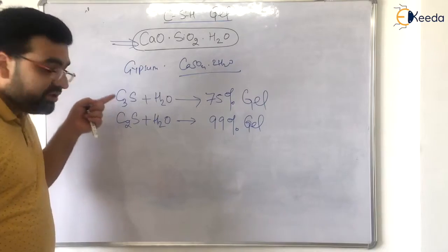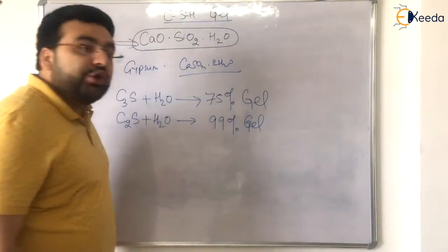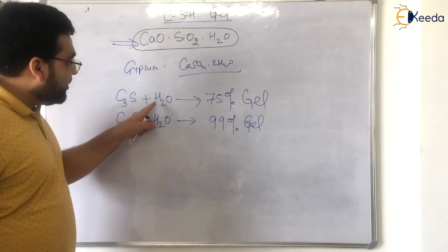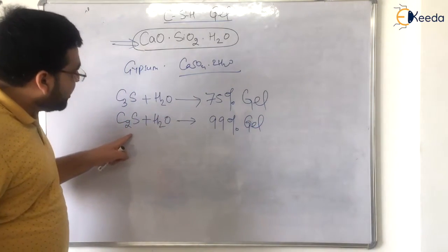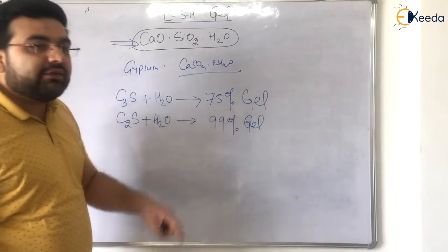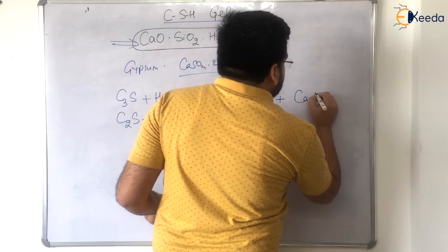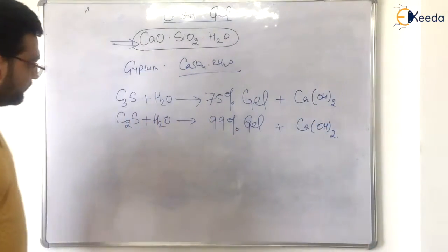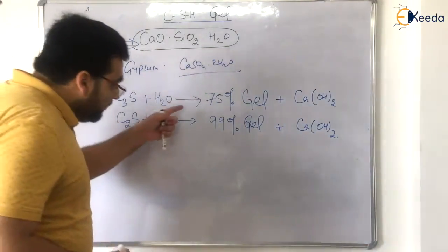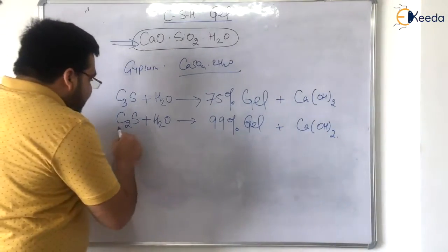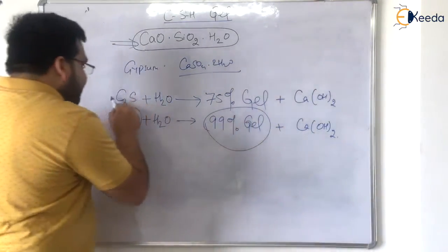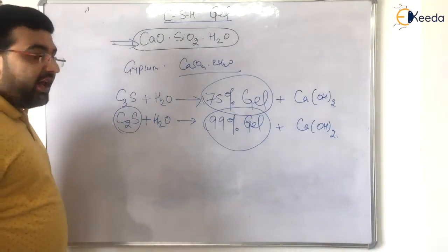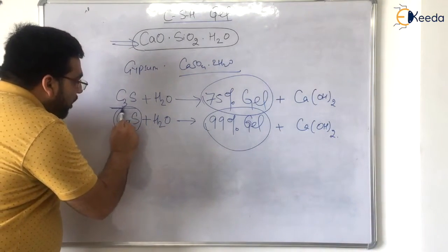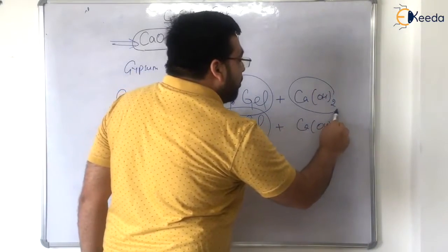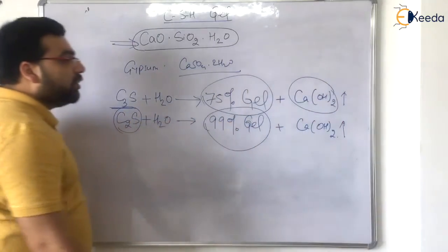Very important. The thing which I am just telling you is very important, because one question was asked a few years back. If tricalcium silicate or alite reacts with water, it forms 75% of gel. If dicalcium silicate or belite reacts with water, it forms 99% of gel, plus some amount of calcium hydroxide is also formed. You know that C2S forms 99% of gel, C3S forms 75% of gel, and it has been found by experiments that if water reacts with C3S, then the percentage of Ca(OH)2 is more as compared to when water reacts with C2S.